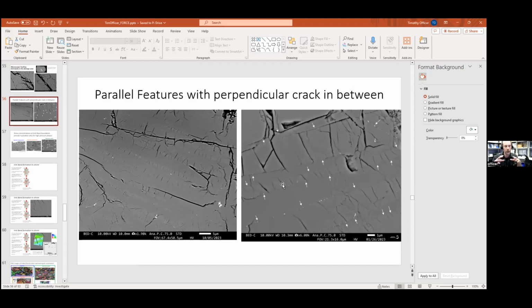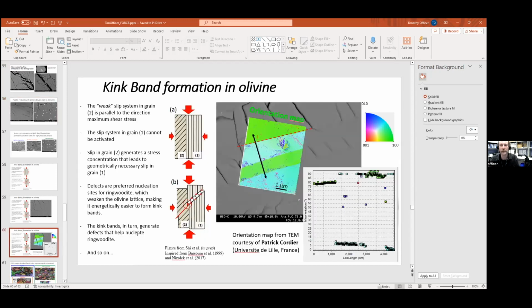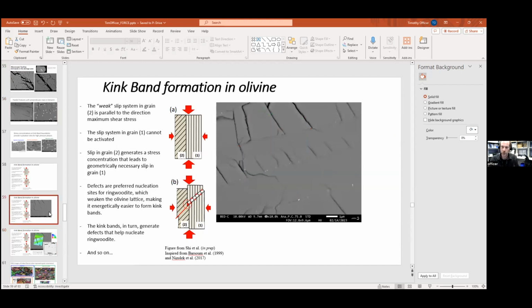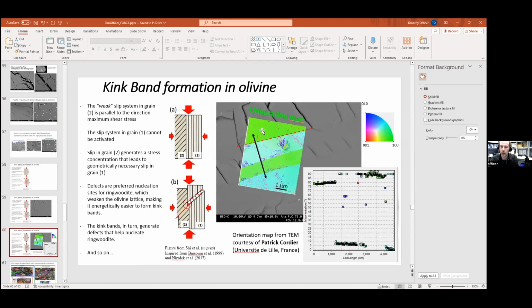These little cracks don't happen under high pressure. They happen when we unload the sample. And I think it has to do with the anisotropy, because olivine's not isotropic. If you look at the orientations across these things, here's the original picture, and then as you move across it, you see that you're flipping orientation. At the beginning we're at about 80. These are just relative. Then it goes to 0 and back up to 80 and to 0. But if you're looking for a nice TEM image of grain size, I don't really have one. Sorry, which I think is what you wanted to see.